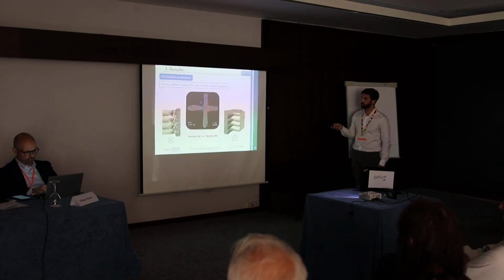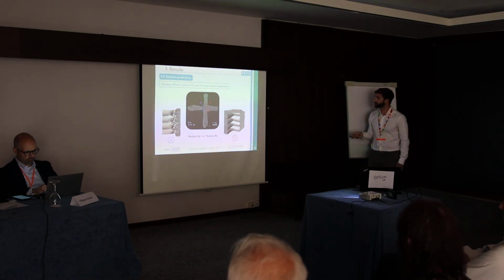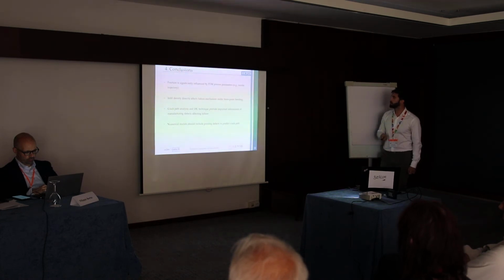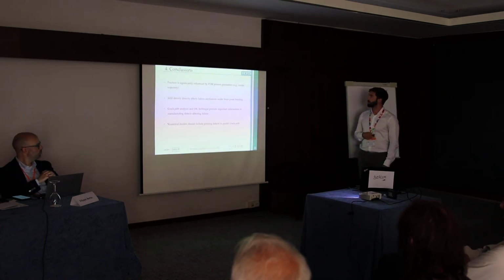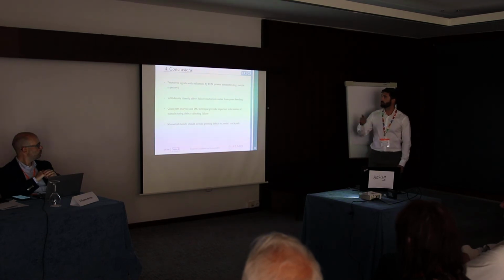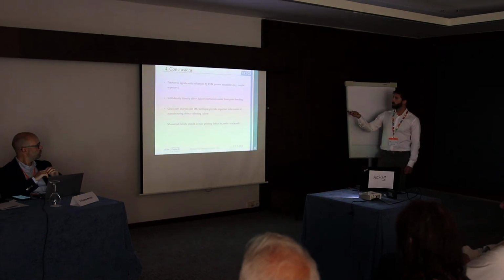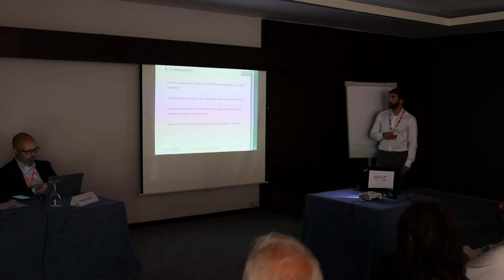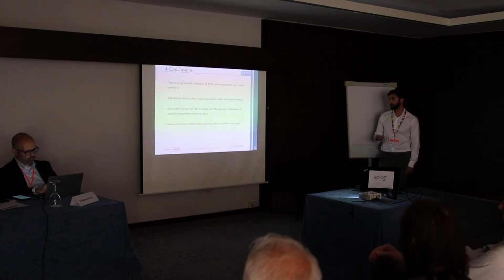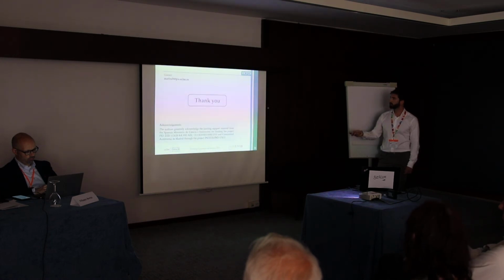And as a conclusion, very fast, the fracture is significantly influenced by FDM process parameters, like the nozzle trajectory, of course, as we studied. The infill density directly affects failure mechanisms in three-point bending. The crack path analysis and DIC technique provide important information on manufacturing defects affecting failure. And numerical models should include printing defects to predict the crack path, as we see here. That was everything. Thank you so much.